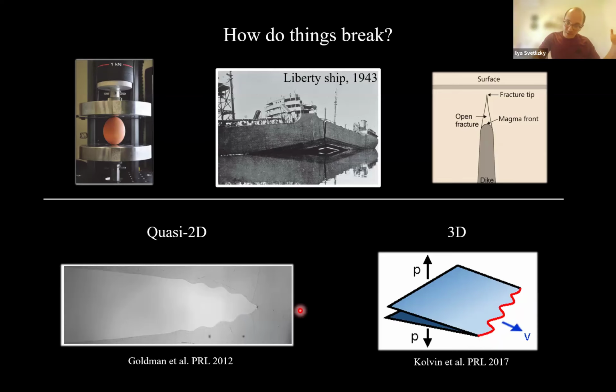So Jay Fineberg and his group and other groups around the world have addressed the 2D fracture, and we have quite a lot of understanding. We have a very good description of how cracks in quasi-2D propagate. The challenge in 3 dimensions is to model the variation along the crack front line. And from a theoretical perspective, the math is getting very, very ugly. And from an experimental perspective, the challenge is first to be able to visualize the crack front in 3D. And second is to do that fast enough so you can capture the dynamics.